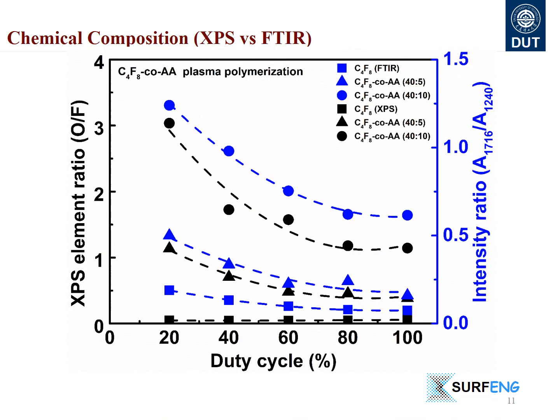A slight increase in carboxylic to fluorocarbon FTIR ratio is due to decrease in fluorine intensity, which suggests less free radicals are available for polymerization during longer off time. Polymers show a linear increase in carboxylic to fluorocarbon ratio and oxygen to fluorine element ratio by lowering the duty cycle. These results demonstrate that variation of duty cycle can provide fine control over chemical composition of plasma copolymer coating.